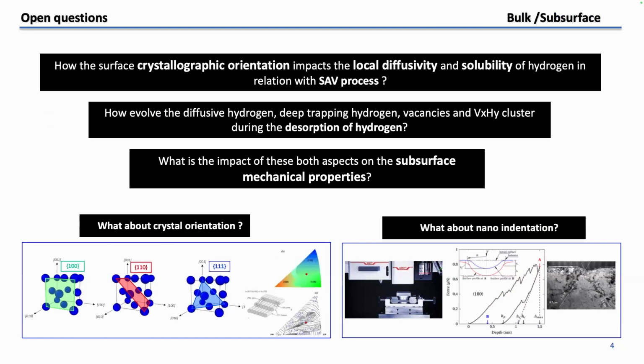Well, first, we tried to question the impact of crystallographic orientation on the local diffusivity and solubility. We present some results of our lab on that. Then, in the second step, we tried to follow the evolution of diffusive hydrogen, deep trapping hydrogen, vacancy and vacancy clusters during the desorption of hydrogen. And then we can try to discuss the impact of both processes on mechanical properties. And we use different crystals, 100, 110, and 111, and also we have another orientation.